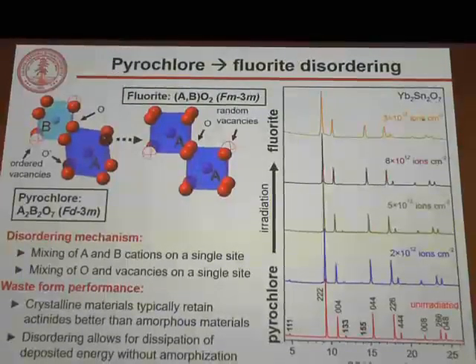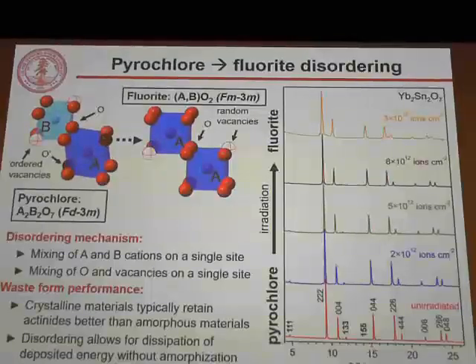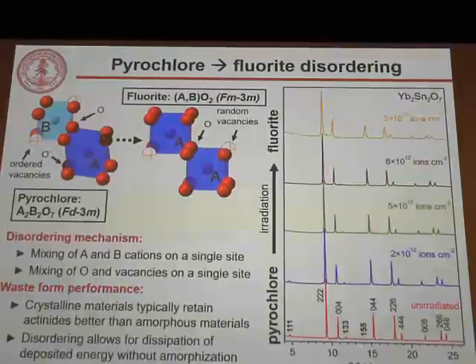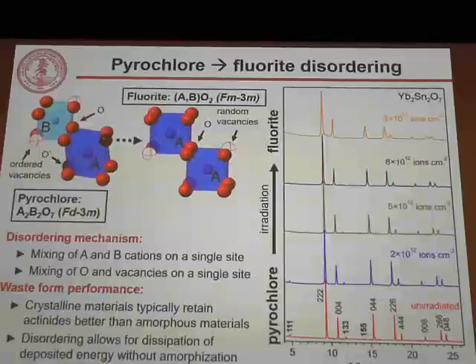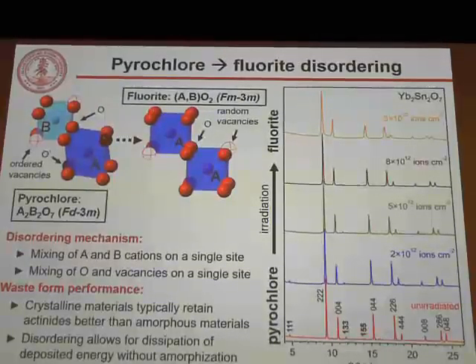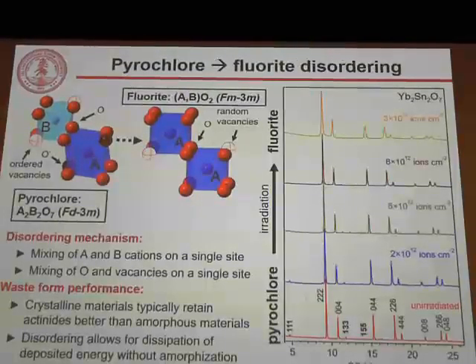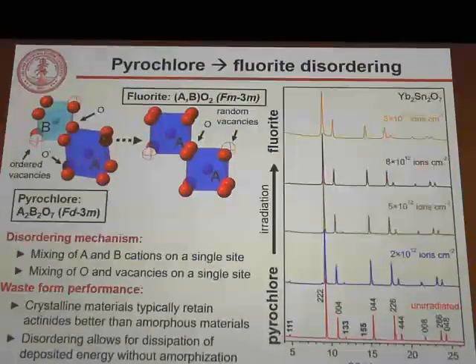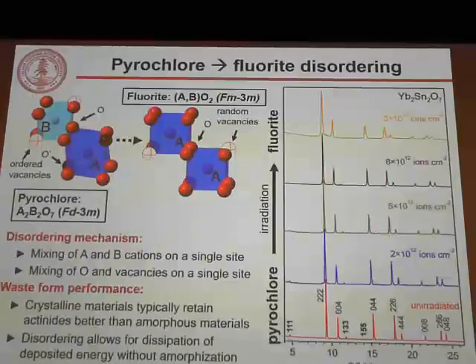So I show here XRD data for what happens when we irradiate one of these radiation-tolerant pyrochlores, and you see that as we move from bottom to top, these intense peaks corresponding to the fluorite substructure are retained, and we only lose these very weak peaks corresponding to the pyrochlore superstructure. But yet, even at very high ion fluences, as shown in orange, the material remains crystalline. It still has clear XRD diffraction maxima.